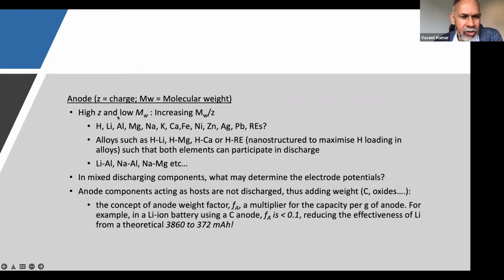So now, again, using the charge and the molecular weight, I have ordered these elements in increasing molecular weight divided by Z. So obviously, if we could get solid hydrogen or in a host, that of course will have the highest energy density. But that's not easy to achieve because some of the materials in which you can hold hydrogen and then use as a battery are themselves very dense, so you lose that advantage. So that's the reason why lithium is extremely popular. Yes, that ratio is about 7, so it stands as the best solid anode possible.